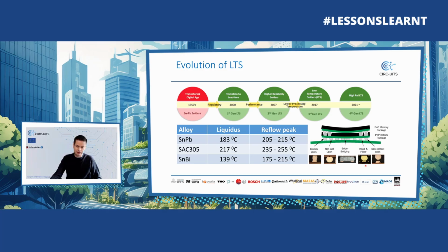You can see them here, head and pillow. I'm not going to explain everything of these defects. That will be too long. But to overcome this, we worked on new alloy technologies. So we, as the industry, the suppliers of solder material. And the alternative we came with was a tin bismuth alloy. So that was the first generation of lead-free low temp solder alloys. It has a liquidus of 139 degrees C, so you could reflow at 175 to 215 degrees C.